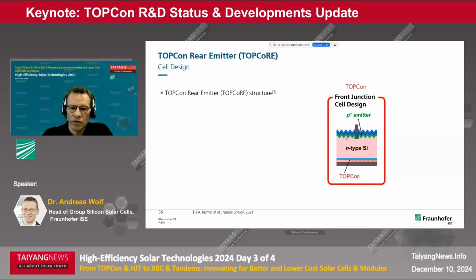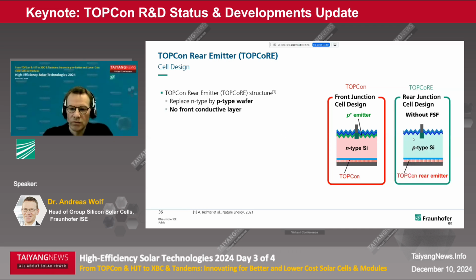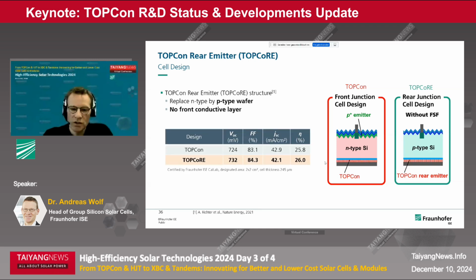design. Here you see the conventional TOPCon structure, and compared to this, the TOPCORE structure switches from N-type to a P-type wafer, and it also omits the conductive front layer on the front side. And this gives some advantage in efficiencies, as we could demonstrate at that time with record efficiencies, due to omitting the inherent recombination that is coupled to the presence of this highly conductive layer. I will share some details on this now.